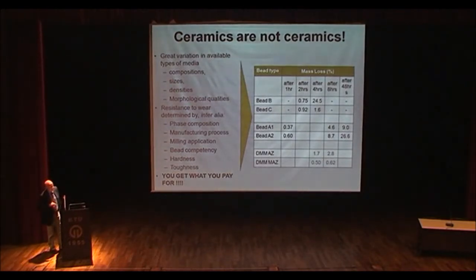Sizes, we produce a range, in mass range, from 0.2 millimeter right through to 5 millimeter. The conventional sizes at the moment are 2 millimeters, 3.5 and 5 millimeter sizes, but you can have smaller ones. The density, invariably you have three densities. You have the alumina species, which are all around about 3.8. You have the zirconium silicate, which is made from pure zirconium silicate, at around about 4.2, 4.3.